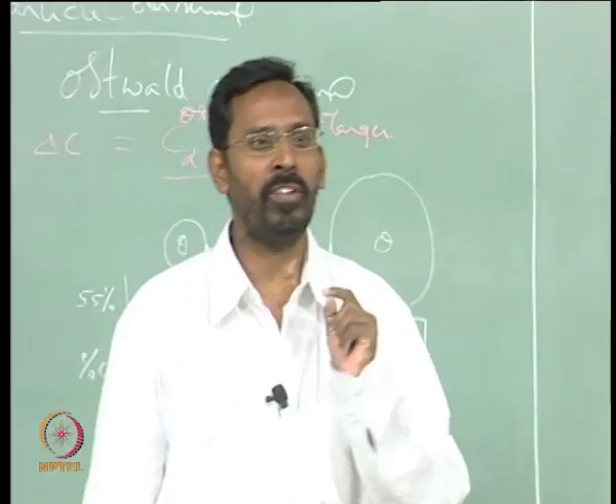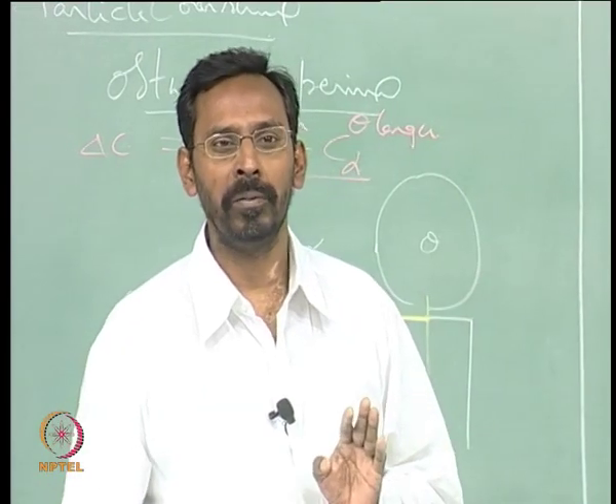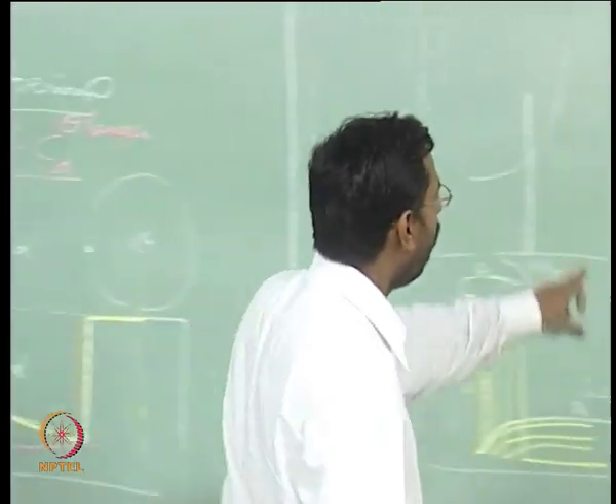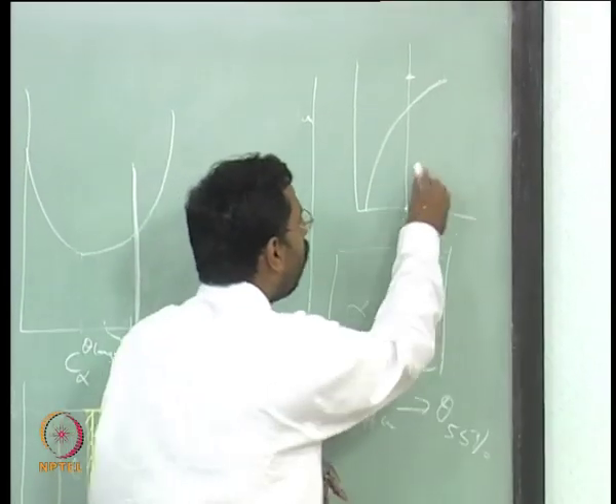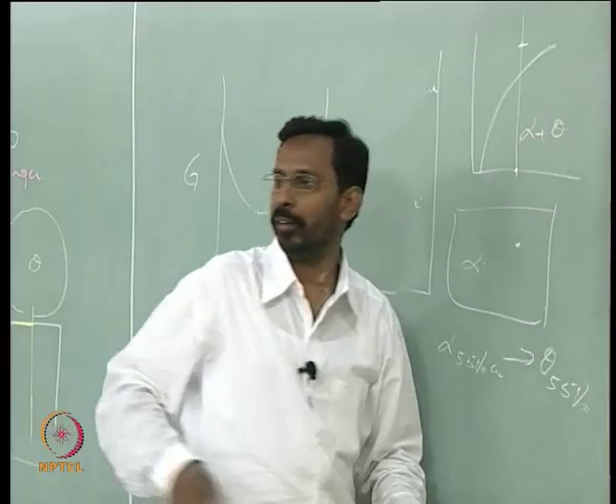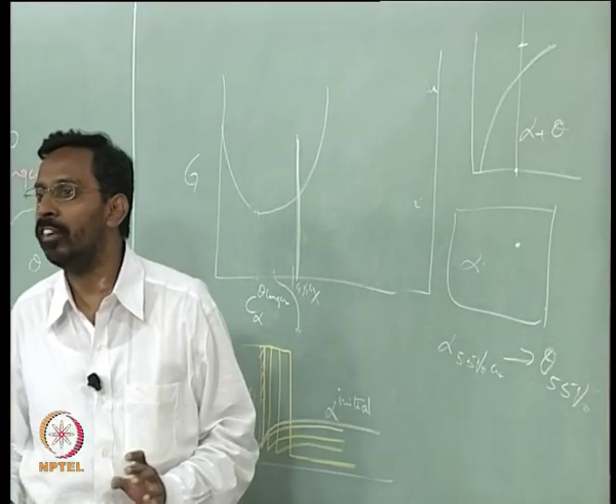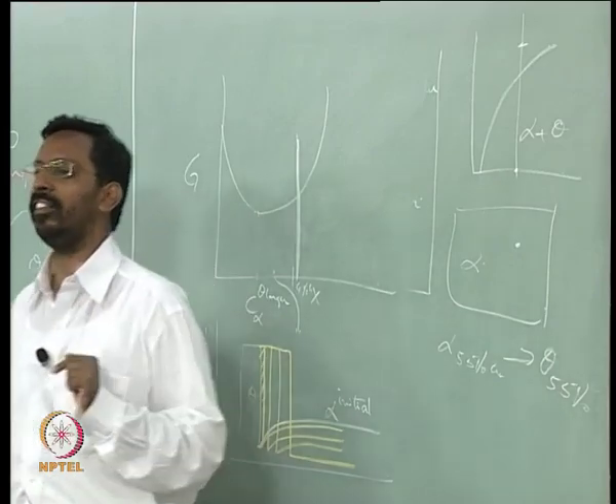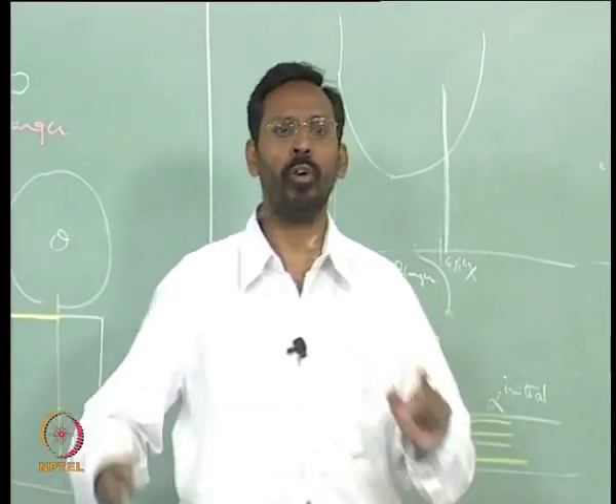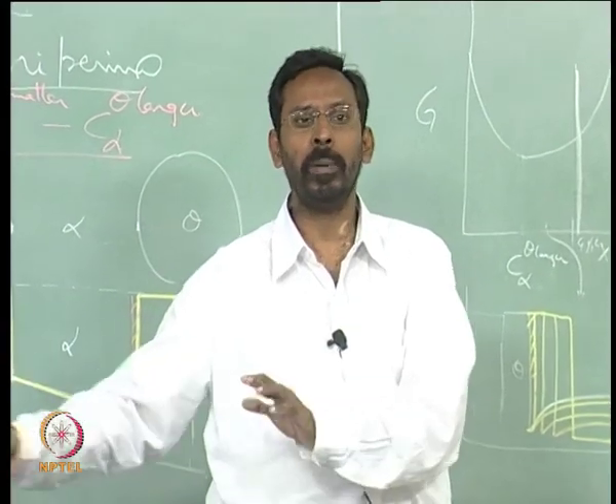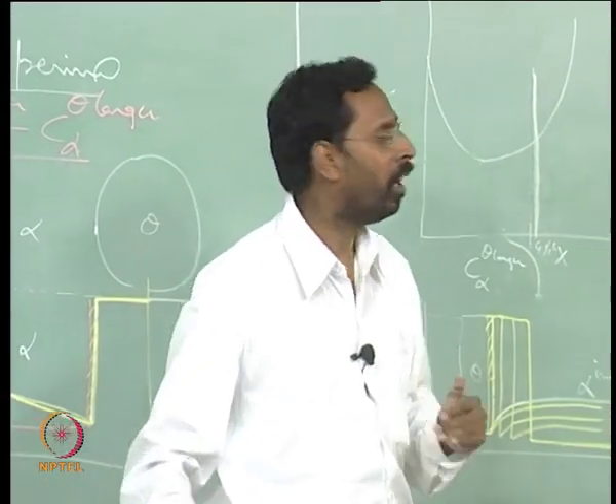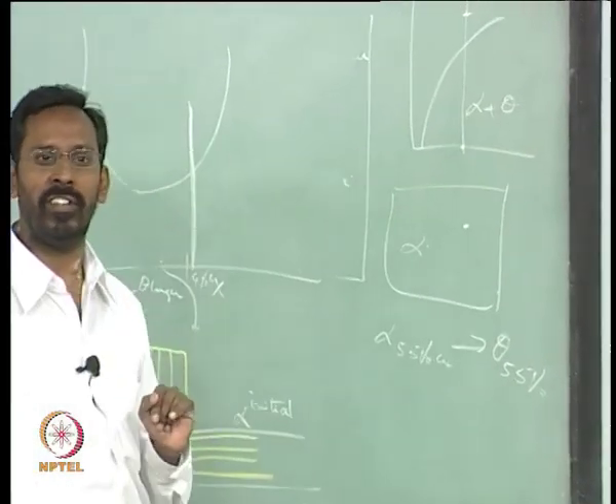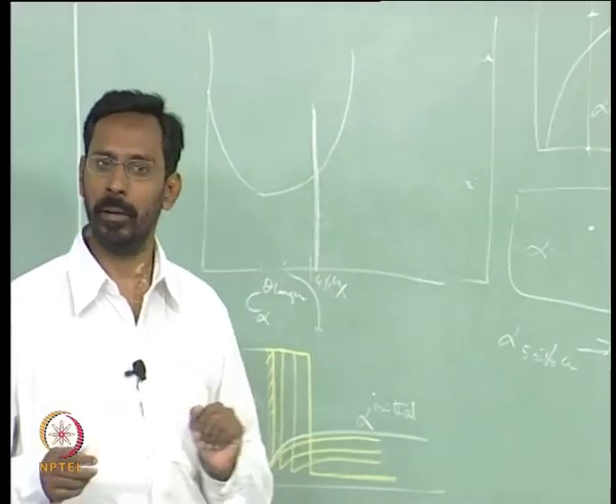Be very specific when you say alpha is not stable. In the equilibrium phase diagram you still have alpha plus theta. We cannot say alpha is not stable. Alpha as a single phase is not stable. Alpha can coexist with theta for that particular composition and temperature. And now, if it is not stable as a single phase, it wants to precipitate.